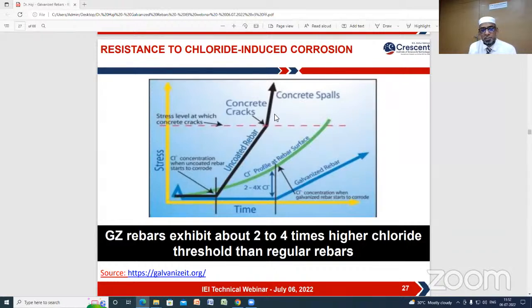So within a shorter time duration, the corrosion initiates, and accordingly it propagates in a faster manner, leading to an early premature distress. In the case of galvanized rebar, it will take a longer time for corrosion initiation. Only when the chloride reaches this level does the corrosion initiation happen. That means the period for corrosion initiation is at least 2 to 4 times longer compared to the conventional rebar. After that, it slowly starts corroding. Here also zinc only corrodes and protects the steel. Finally, it will offer a very good design life without repairs. In a nutshell, what we have to understand from this diagram is that galvanized rebars exhibit 2 to 4 times higher chloride threshold than the regular rebars.